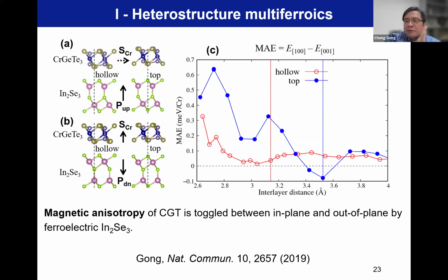So how to use a small voltage to control? We use an idea that existed in the multiferroic community. Basically, you have a Van der Waals heterostructure here, where the 2D magnet is chromium germanium telluride and the 2D ferroelectric is indium selenide. The DFT calculation shows that if you polarize the ferroelectric indium selenide up or down, in figures A and B, the calculated magnetic anisotropy of CGT is in plane and out of plane, as illustrated in A and B. So you can see a ferroelectric control of the magnetic anisotropy of 2D CGT.